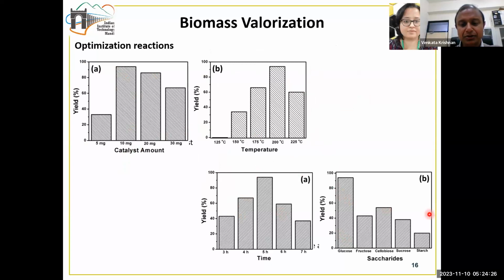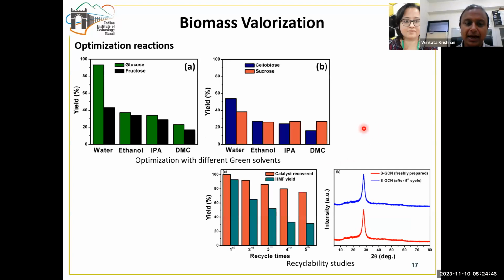Then we tried the reaction using different saccharides, which include glucose, fructose, cellobiose, sucrose, and starch. And we found glucose gave the higher yield of the product. Although all these saccharides give the selective product, 5-HMF, the yield is different for different saccharides, and glucose gave the highest yield among the explored saccharides. Subsequently, we also tried different solvents, which include water, ethanol, IPA, and DMC, and found water to be the best or optimal solvent for this reaction, for both glucose and fructose, which are the monosaccharides, and also for the higher saccharides such as cellobiose and sucrose.